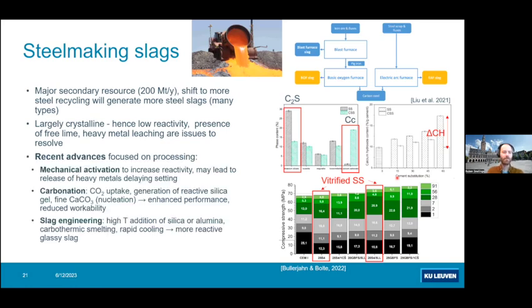Recent advances have mainly been focused on trying to reprocess these slags. So mechanical activation seems to work to some extent to increase reactivity. Carbonation may work as well to increase CO2 uptake in the material, but also generate reactive silica, as we've seen for the recycled concrete fines.